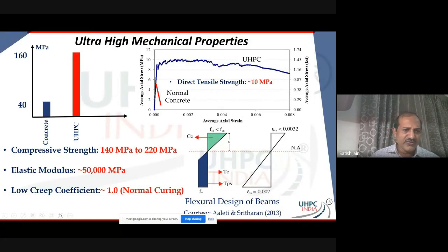So what's the advantage of these three things that I just spoke about? See, when it comes to long span, you can put a whole lot of pre-stressing in it and still keep going longer, right? Because the more the compressive strength, you can put in more pre-stressing. And long spans have deflection related issues. That's where the elastic modulus helps, and also the low creep helps with the long-term deflections. So this is a great recipe when it comes to doing long span structures with UHPC. And you can do a lot of short span also, right? But it's a great recipe to put pre-stressing in as well.